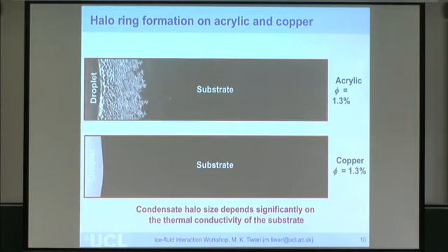Now this vapor is at minus 15 degrees centigrade. It's got nowhere to go but to condense down, and so it does. Now I have the humidity in my chamber down to 1% or so, so that condensate starts to evaporate as well, and some of it can touch the original droplet and form this frozen ring as we are talking about. We call this the freezing halo, not my term, somebody else's term, my supervisor in Zurich, but it does look like a halo around the droplet, so fair enough.